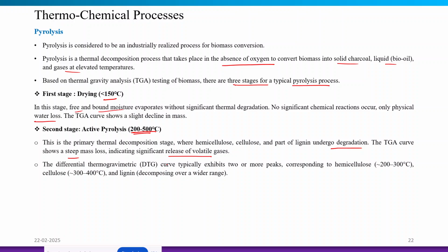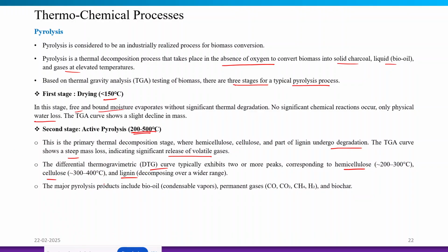From the TGA DTG curve, the DTG curve typically exhibits two or more peaks. The peak at nearly 200 to 300 degrees Celsius denotes hemicellulose degradation. 300 to 400 is cellulose degradation, and after that there is a broader degradation range for the lignin. The major pyrolysis products in this active pyrolysis are bio-oil and some gases, carbon monoxide, carbon dioxide, methane and hydrogen, as well as biochar.